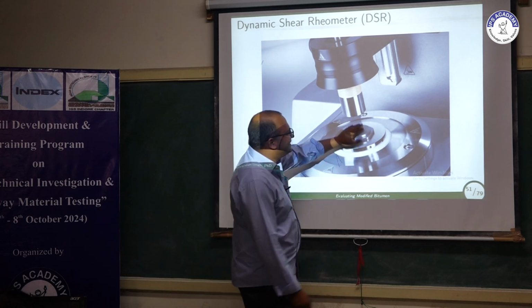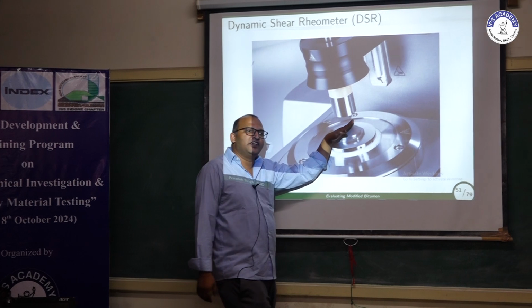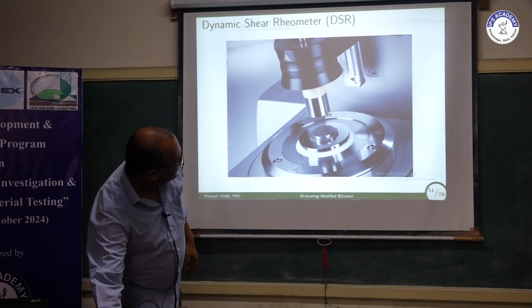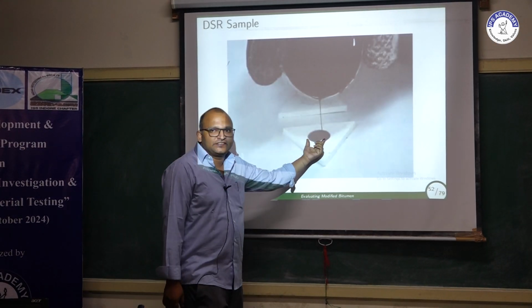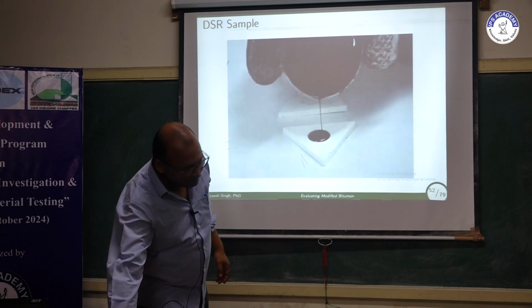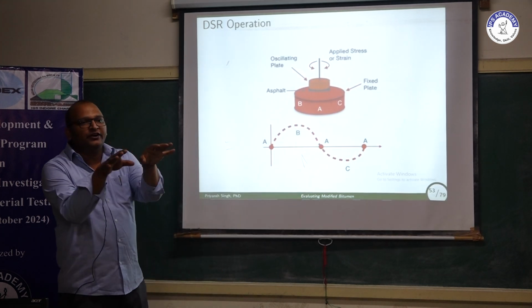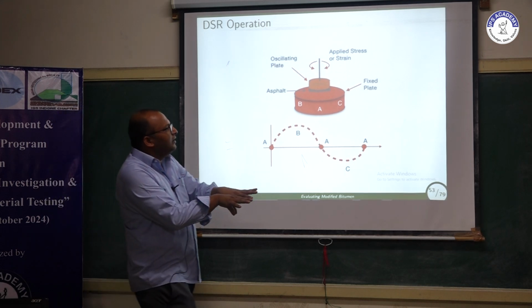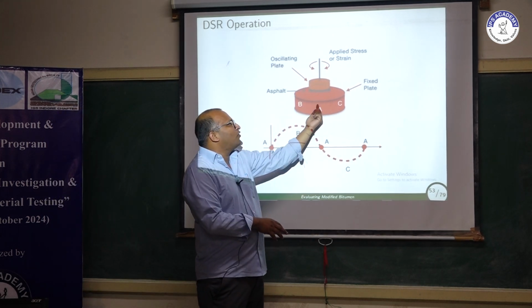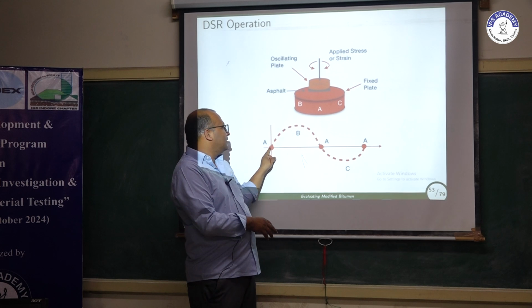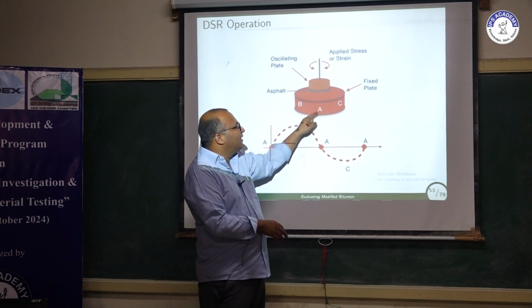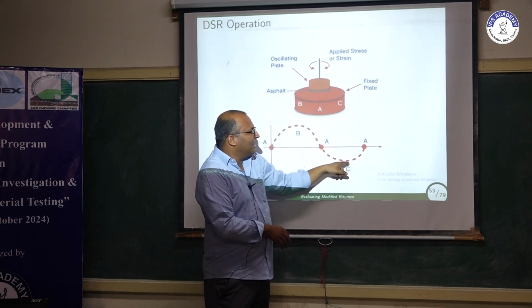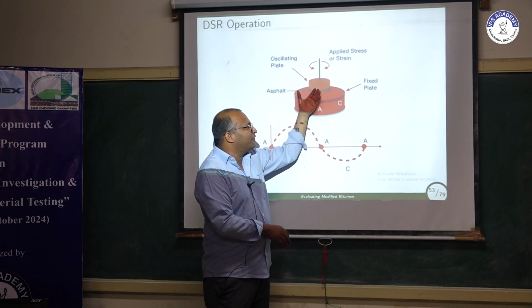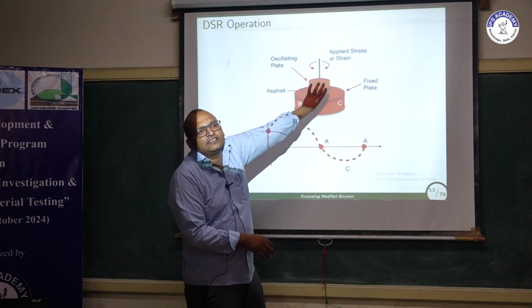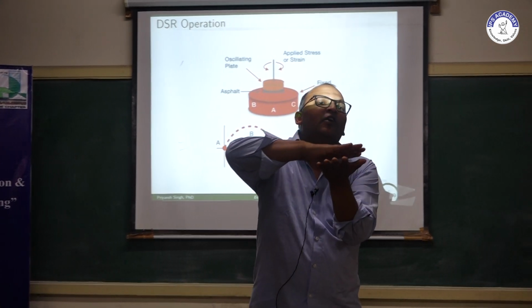So here you can see two plates. We'll put our binder here in between these two plates. This is the kind of binder sample required, and then we will load the binder. The plate will move from A to B, B to A, and then A to C, and then C to A. That means a half rotation this side, then again a half rotation this side. So this will generate a shear on the binder, a half shear, then again a half shear.